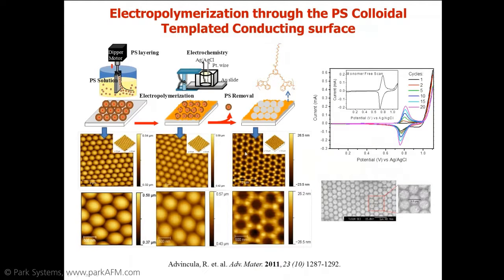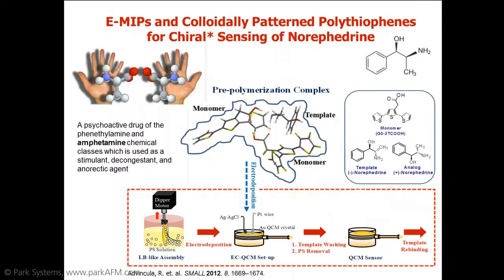That means that we can create conductive polymer patterns of a high surface area or accessibility to an analyte compared to a flat film. So we dramatically increase the surface to volume ratio advantage by doing this patterning. This was actually demonstrated on several fronts. But here we refer to the use of these patterned surfaces for distinguishing the chirality between norephedrine analogs.